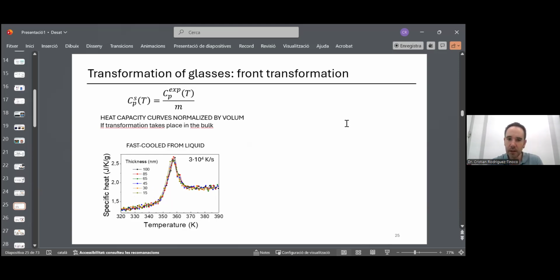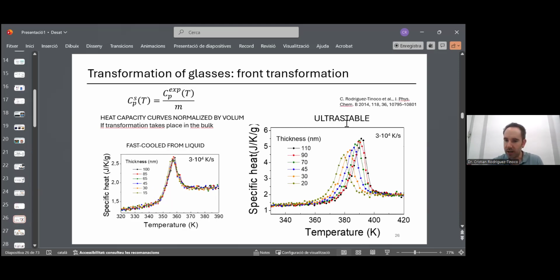So specific heat should be the same regardless of the thickness. Now, we do the same for ultrastable glass. We said before, this is at least at this moment the hypothesis, that ultrastable glasses do not transform via a bulk mechanism, but by front transformation, starting from the surface, propagating into the bulk. So if we now normalize by dividing by the mass, as we did here, we get this. One would say the vitrification temperature depends on the thickness, but if the mechanism of transformation is the one we said, this is not right. This is not true because we are normalizing by the mass. The mass involved in the transformation process is not the same in all samples.